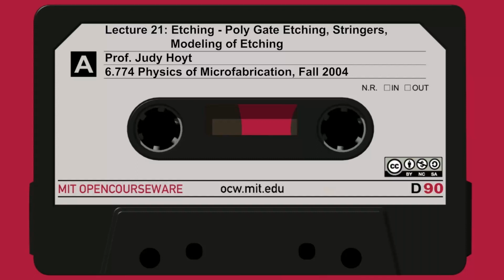When do we etch oxide? In a MOS process, for example, we're often etching oxide when we're opening up contact holes. So we have an interlayer dielectric of some sort, maybe 1,000 or 2,000 angstroms. We need to get through it, and with reasonably good control of the sidewalls, we also need to stop on the silicon. You don't want to etch away your source drains. So anisotropy and selectivity are also very important.